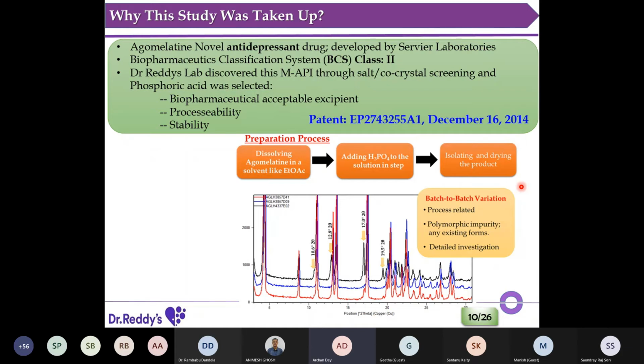We thought okay, but what happened? When we started to take the batches, we started to see batch to batch variation. This is a very preliminary powder XRD study. As you can see, there are such and such peaks coming in the batches. From this we put forward the hypothesis: it could be process related, or it could be a polymorphic impurity of any existing forms. With that thought we took up a detailed investigation.